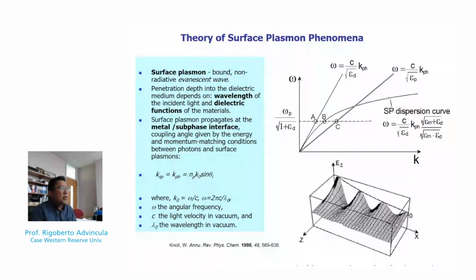So in this case, we treat surface plasmon as a bound, non-radiative evanescent wave, meaning that the light intensity varies with distance from the surface. Its penetration depth into the dielectric medium depends on the wavelength of the incident light and the dielectric function of the materials. So you get different types of surface plasmon dispersions, depending on the dielectric material. And metal versus air or metal versus organic layer provides a very good contrast that makes SPR very useful for applications such as sensors or even photochemistry.